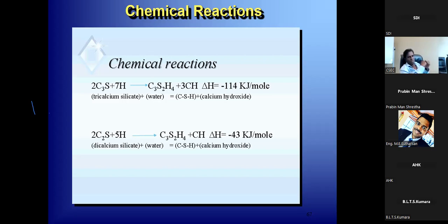That's a very good question from the audience in the webinar. The silica fume has two effects. You are really right. The pozzolanic effect is the reaction of CaOH2 plus SiO2 making a bit more CSH. That's the pozzolanic part. And you are really correct, the particles are very small, smaller than cement, so it has a bit of a filler effect as well. I've got a slide later on, but it's a good point. So it has both effects and will make the concrete a bit more compact. But the strength increase of silica fume comes mainly from this reaction. Of course, the filler effect will make it a bit more compact as well, but mainly it's coming from that pozzolanic reaction. Very good questions.